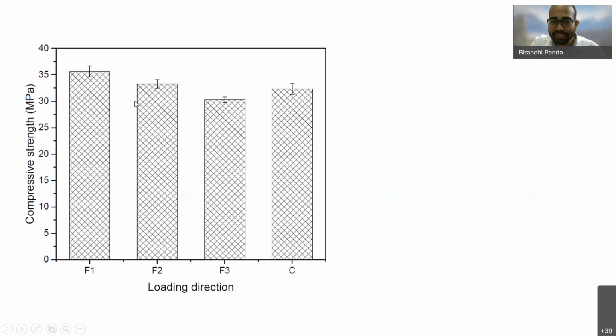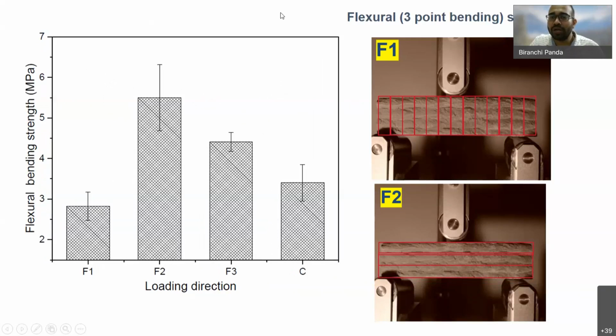But what is most interesting is when you conduct the 3-point bending test, because here these two directions are very critical. In the F1 direction, if you want to apply force, the strength is going to be very low, because in this sample the bond strength between the layers was very poor. So if you do this 3-point bending test in the F1 direction, we ended up with a very low bending strength, but in F2 we got the highest strength.